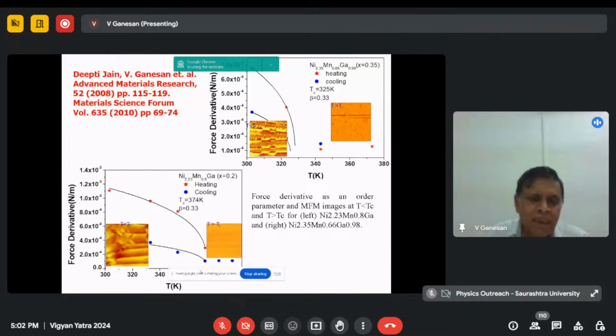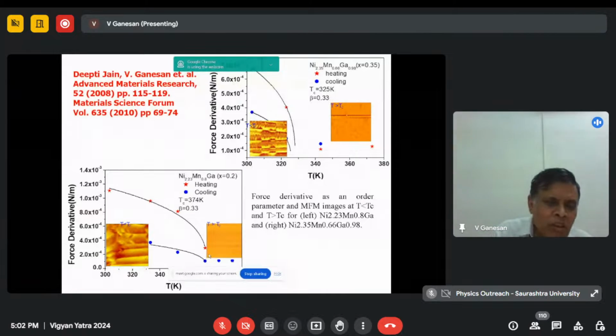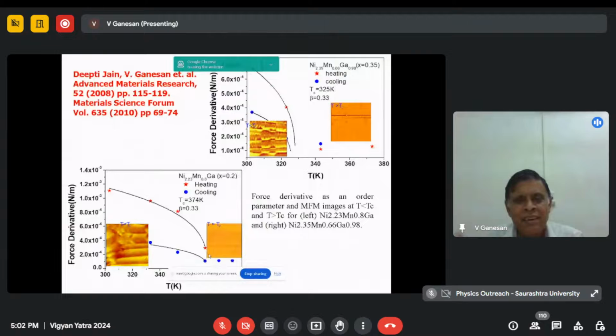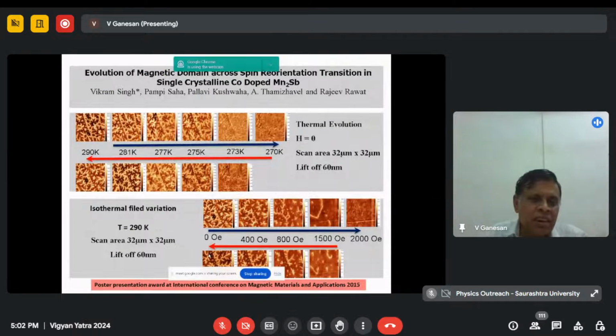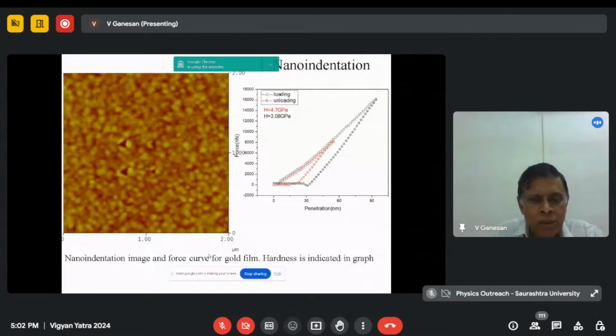So you can study the magnetic transition, the coupled magnetic transition, how it goes. The Tc can be estimated and compared to magnetism. Something like a macroscopic measurement, versus a microscopic measurement of one single domain to study its properties. That's what I want to say: AFM is not just seeing things, it can also do that. And similar work has been done with magnetic force microscopy as a function of magnetic field by Rawat's group. They are much better at it.